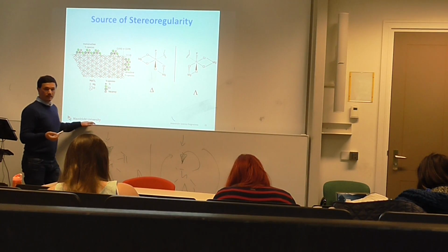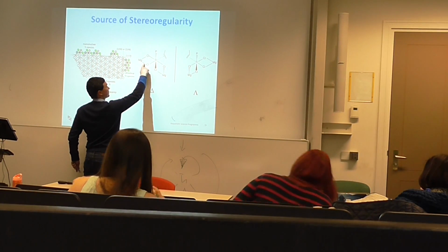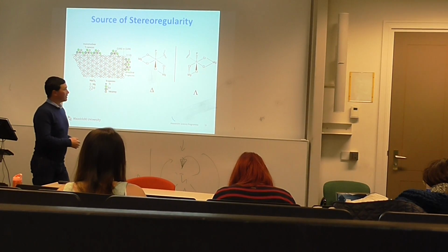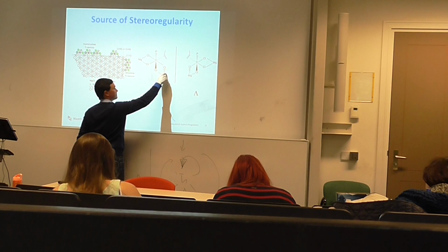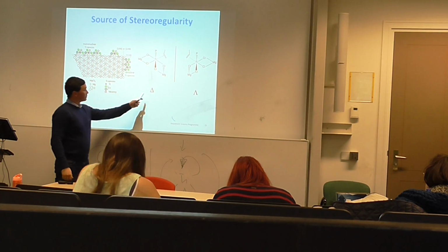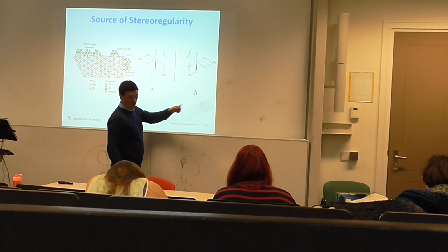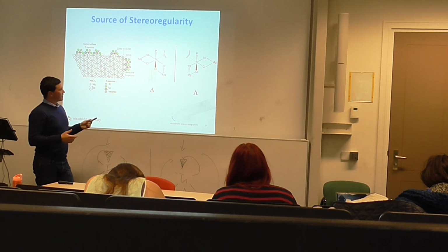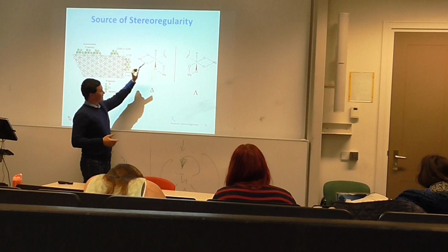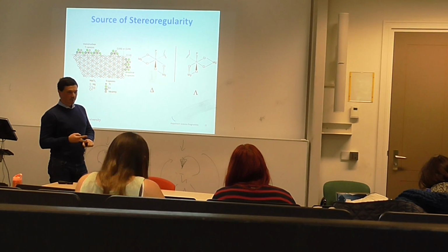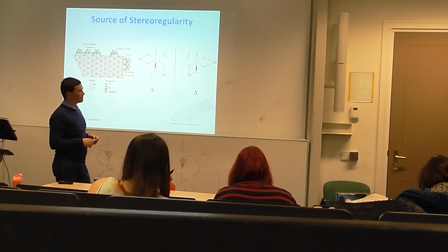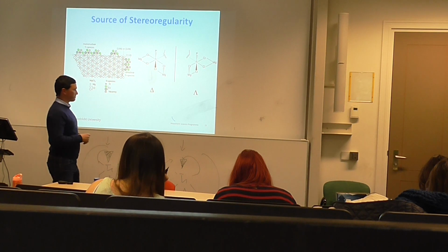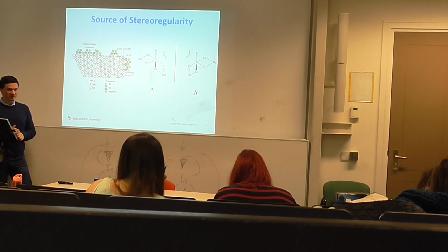Where is your bidentate ligand? It is the chlorine, which is connected to a magnesium in the crystalline structure of the catalyst itself. So you have to look at this like a bidentate ligand. So this is going to be delta, this one is going to be lambda. Okay? So because there is stereoselectivity, let's say this metal here is coordinated with two bidentate ligands in a delta fashion, it will take one preferential face of the propene. Better? More clear?